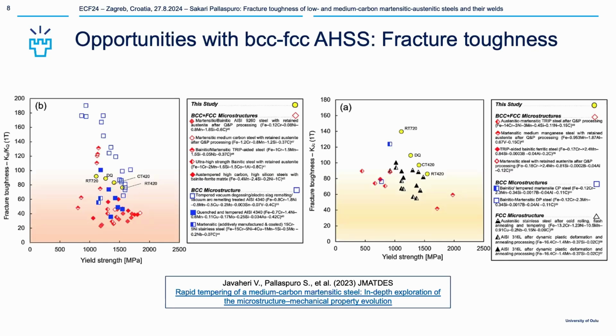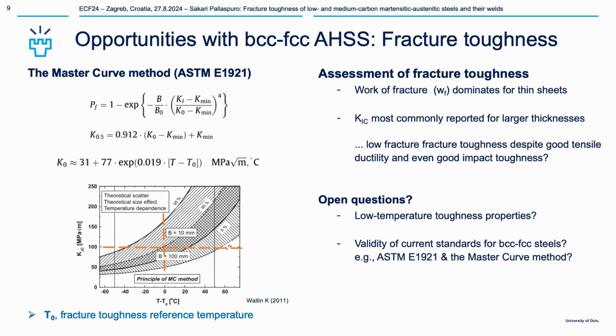only elastic values. Jumping into the elastic-plastic fracture toughness values, we also see that around the range of 100 megapascal square root meter, you can achieve it with a wide range of yield strengths. This was actually our study on rapid tempering of these quenched materials: can you retain the strength and still recover deformability in the Martensitic microstructure with these optimized rapid treatments? So, to the integrity part, the assessment of these toughness properties.